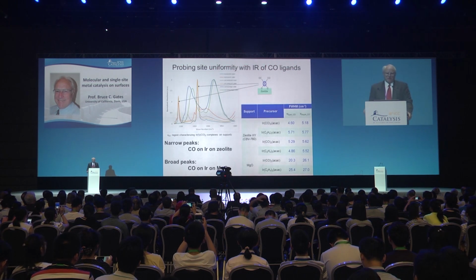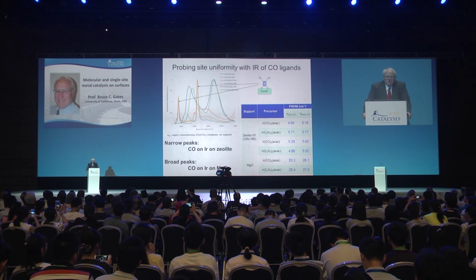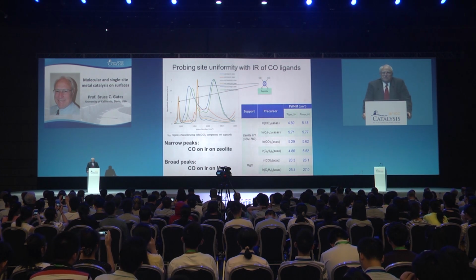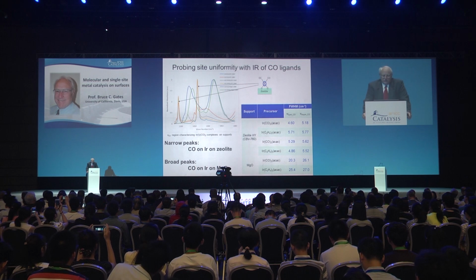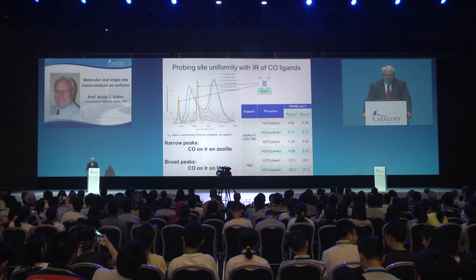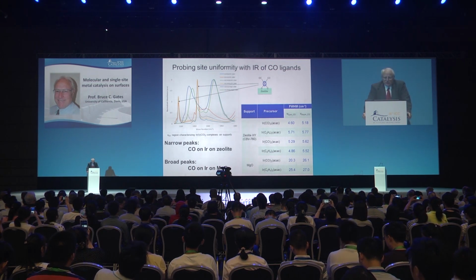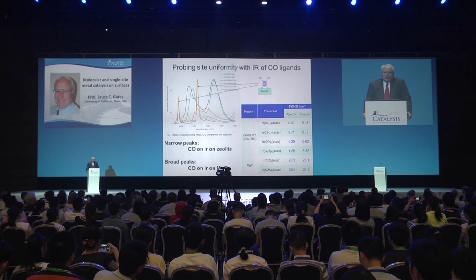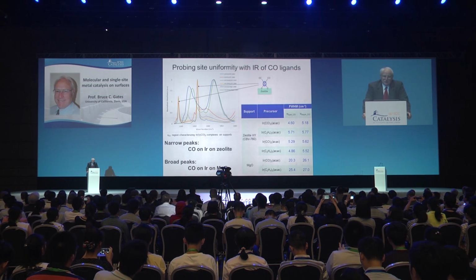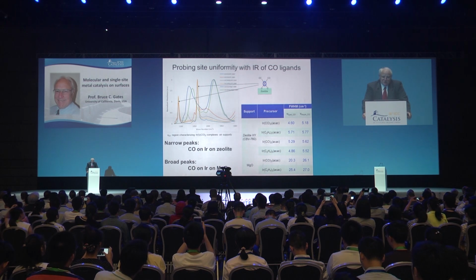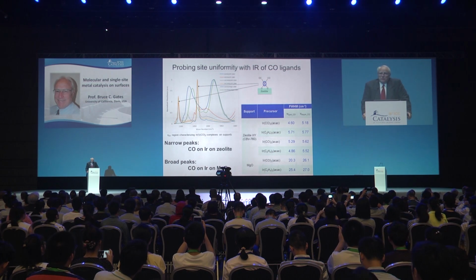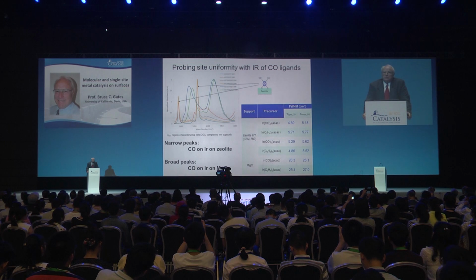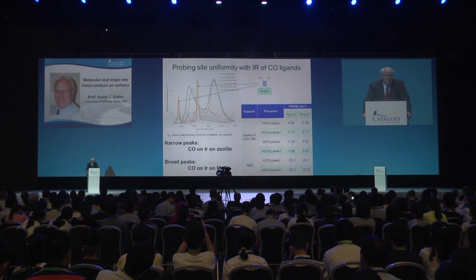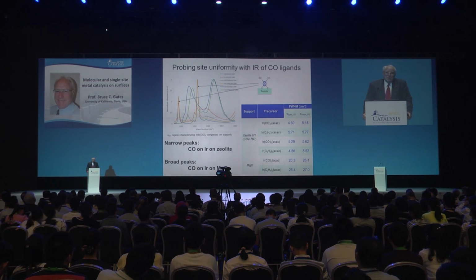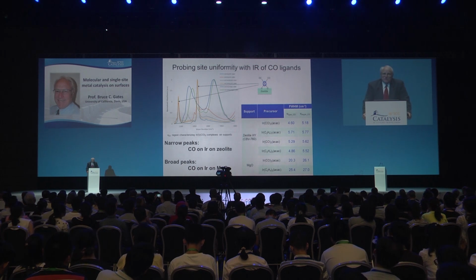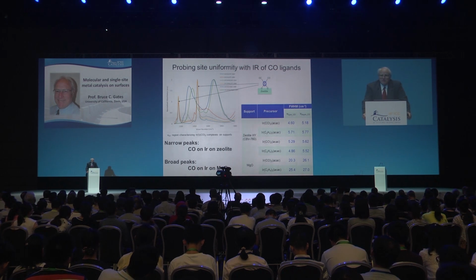So here you see some infrared spectra. There are two points to make from this set of infrared spectra. For the zeolite supported sample, you see the cartoon of it in the upper right, the iridium gem dicarbonyl. The bands are sharp—full width at half maximum about 5 wave numbers—and we can do even better than that sometimes. That's an indicator that the sites to which the iridium carbonyl is bound are almost all the same.